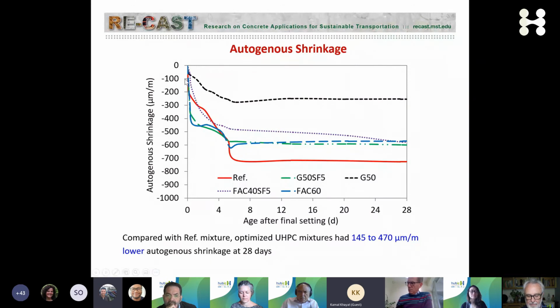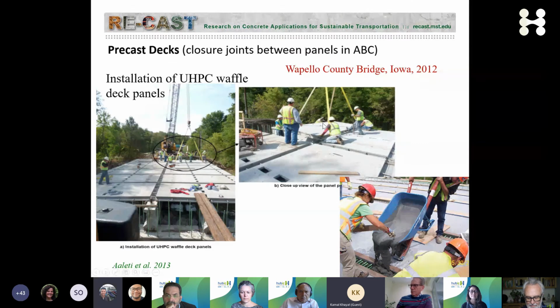And then if you look at the shrinkage, this is autogenous shrinkage. That means chemical shrinkage and self-desiccation, which is very, very high, 700 microstrain for reference concrete. By using supplementary cementitious materials, we can reduce that quite a bit, and that's important for service life.